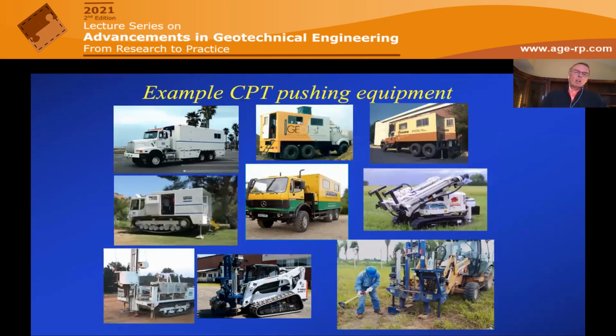Here's an example of different types of pushing equipment. Up in the top row there, you see these trucks. Top left-hand corner is actually one of the trucks here in California. They're typically 25 tons or 250 kilonewtons, and you push from the center of gravity. And so you can push the full 25 tons on this relatively small diameter probe, so you can apply a very large tip stress. You can apply tip stresses close to 1,000 atmospheres of stress, so you can push through very hard material, as I'll illustrate in a minute.